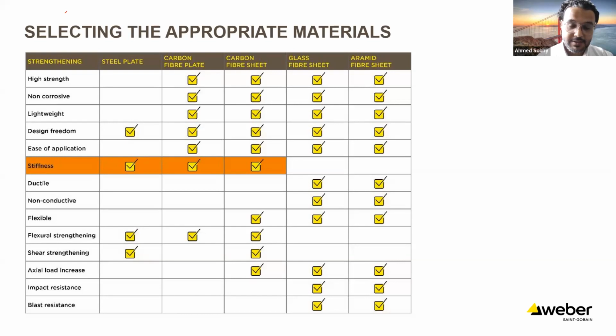The reason is the very low thickness of the material. When we're talking about plates, for instance, we're talking about 0.1 millimeters, 0.3, 0.4 millimeters. So the thickness itself is very, very little, and it doesn't add much stiffness to the structural elements. Obviously, when we want to increase the stiffness a lot, for example to control deflections, we usually specify steel plates, and we still get involved with the specification of steel plates because they're usually installed and fixed using structural adhesive.